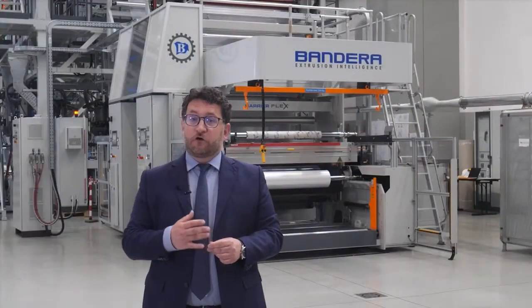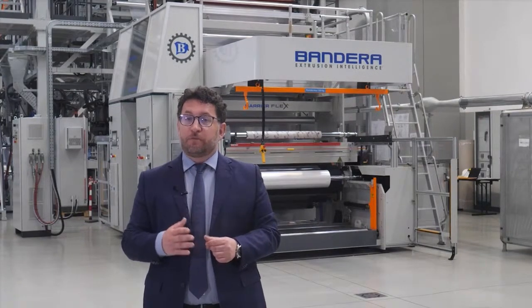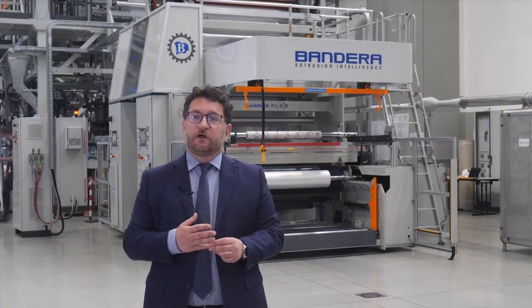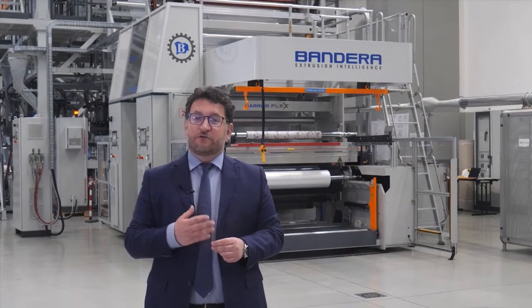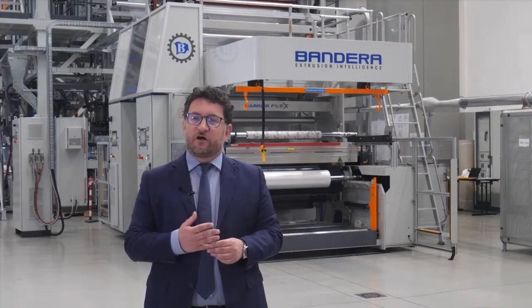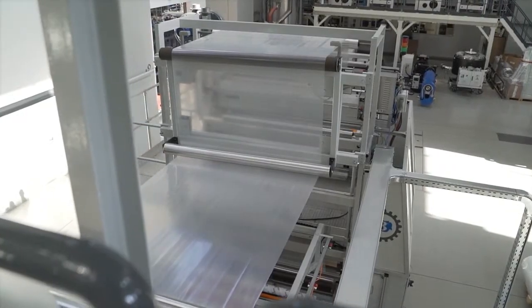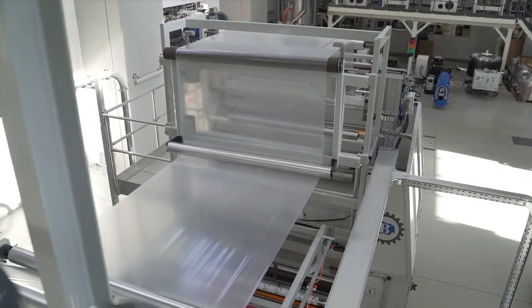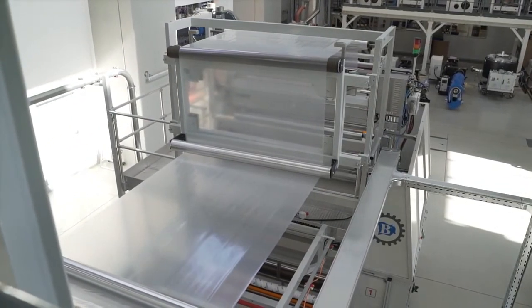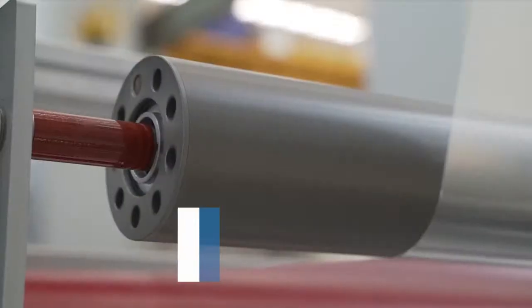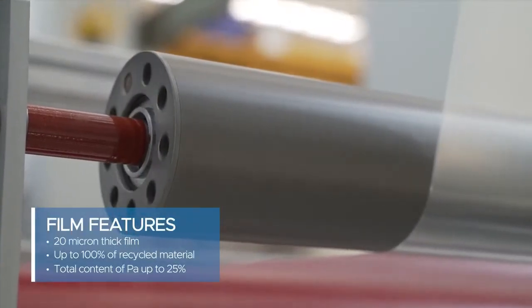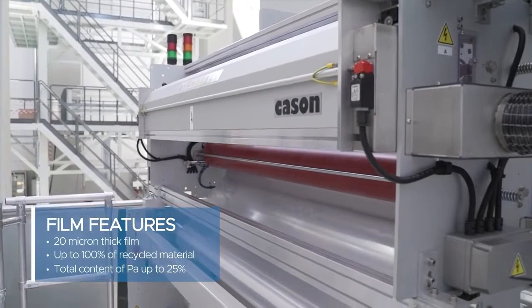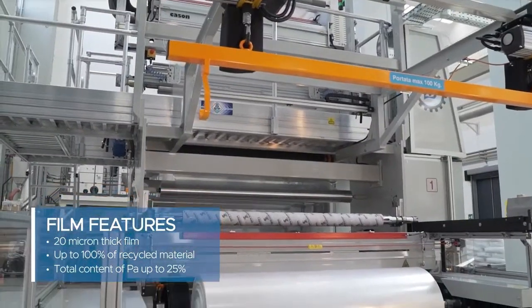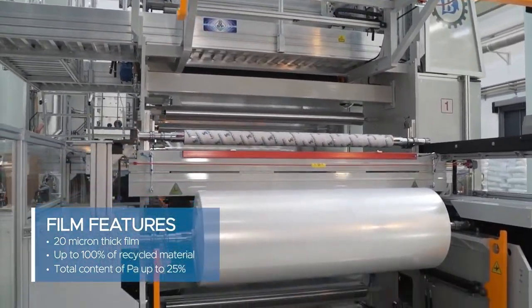Always in a view of constant R&D activities which took place here at the House of Extrusion during the last months, we achieved outstanding and somehow unexpected results, successfully using a polyethylene EVOH polyamide double barrier film on a 3-layer blown film line, running a 20-micron thick film with up to 100% of recycled material, with a total content of polyamide up to 25%.